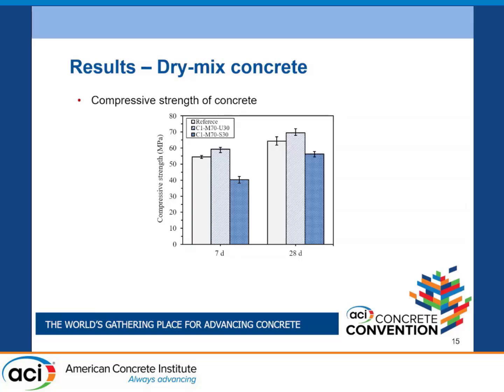This slide presents the results of our dry mix concrete. Again, at 7 days and 28 days, our sample with ultrafine slag has higher compressive strength, but the increase is lower compared to conventional concrete at both 7 and 28 days.